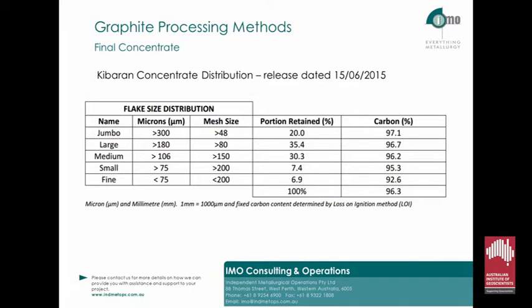You'll notice that the grades quoted in the Kibaran release are from a single LOI, or loss on ignition, analysis. It is acceptable to use LOI measurements for graphite content within concentrates. All that should remain in the final concentrate is graphite and the gangue metal oxides either adhering to or within the graphite matrix, which shouldn't volatilise. We'll still typically get LECO measurements conducted on the concentrate to confirm the LOI measurements, though typically they are lower than the LOI measurements, but I generally expect by less than 1% or 2%.